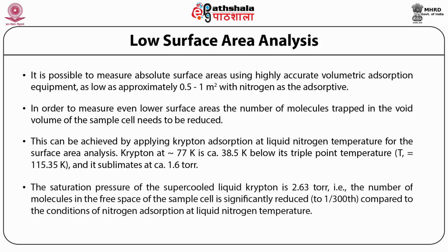The saturation pressure of the supercooled liquid krypton is 2.63 torr, that is, the number of molecules in the free space of the sample cell is significantly reduced to 1/300th compared to the condition of nitrogen adsorption at liquid nitrogen temperature.